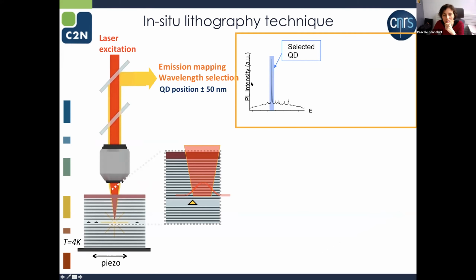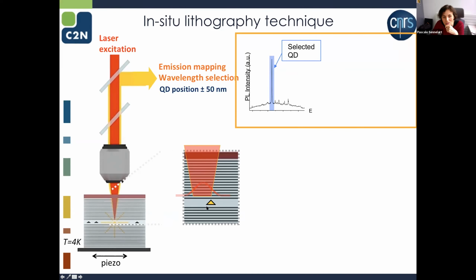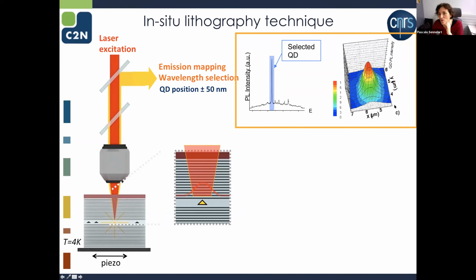And basically what we are doing is that we are scanning the sample with respect to the laser. So we are scanning here my QD, which has a nanometer scale, in a laser that has about 1 micron size. So basically, if I plot the quantum dot signal as a function of the position, I find that there is an emission that follows the laser profile. So it's about 1 micron wide, but it doesn't prevent me to know where the maximum of the curve is with a very high accuracy. And the maximum is obtained when the quantum dot is at the center of the laser, where it is the most excited. So you see that with this technique, we measure the quantum dot position.